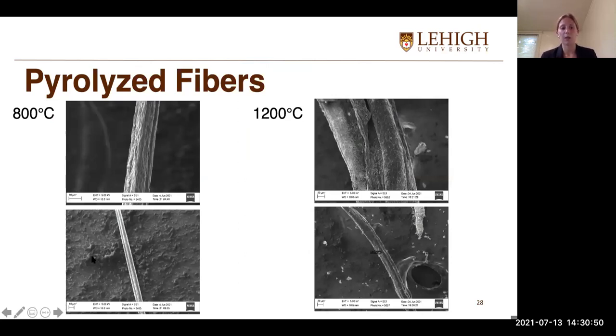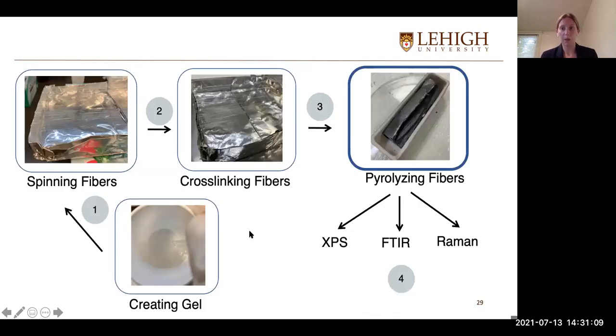So here are some at 800, and as you can see, the surface is pretty uniform as well as the diameter. However, for the 1200, the surface doesn't really have as much of a uniform structure, and the diameter is also not very uniform. And then from there, I was able to do many different characterizations on these fibers. So now I'm going to share some of those results.